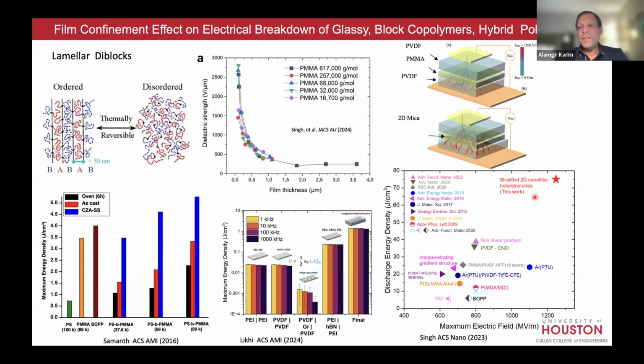And by the way, the amount of filler you add is like 1%. A 15 nanometer sheet is no more than 1% of the mass of the capacitor, whereas in the previous studies, the filler would contribute like 30, 48% of the nanocomposite. And even then, only the dielectric constant went up, but the breakdown would go down with increasing filler.